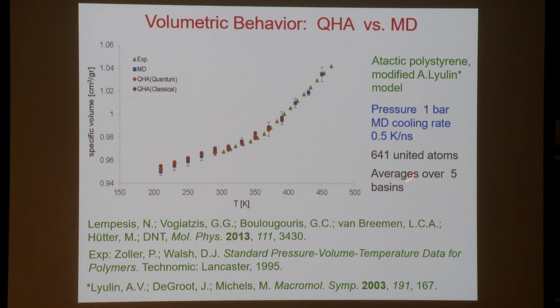Here we have atactic polystyrene with a model that was proposed by Alexei Lulin some time ago. And based on this quasi-harmonic approximation on the expansion that we showed, we calculate the specific volume as a function of temperature under atmospheric pressure. There are results from both the quantum mechanical and the classical treatment of the vibrational motion. At these temperatures, they are practically identical because the temperatures are quite high. And we see that they produce an expansivity which is significantly lower than in the melt state, where we can calculate the volumetric properties by molecular dynamics. So we get this change in slope of the volume versus temperature curve that is associated with the glass transition. And in this particular case, the model is good, so agreement with experiment in terms of volumetric properties is quite good. These are results from averaging over 5 basins.